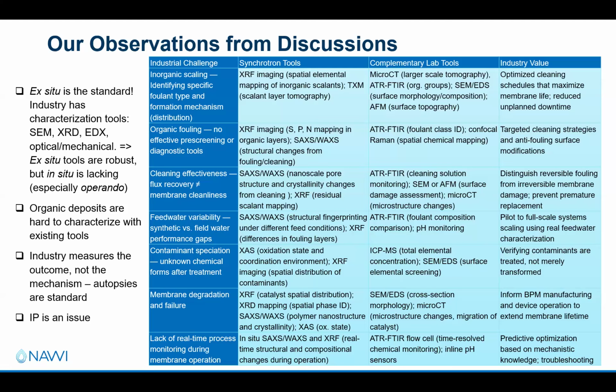Another thing that is quite difficult is figuring out what the organic deposits are on the membranes, because a lot of the membranes are polymeric. And so it's hard to really distinguish what's depositing after the fact from that polymeric material underneath. Then oftentimes we talk to people and they conduct autopsies. And so those are really also just after the fact measurements. Another big issue is IP. So there, I guess, needs to be an avenue for dealing with that.